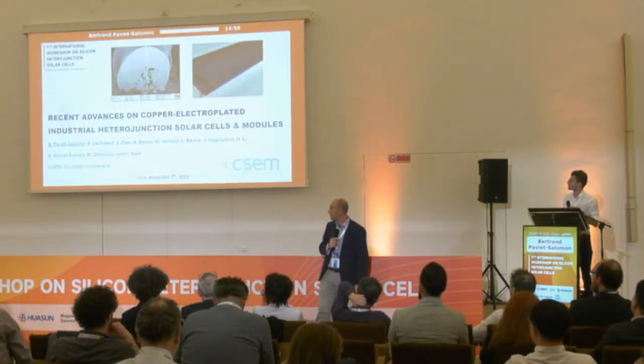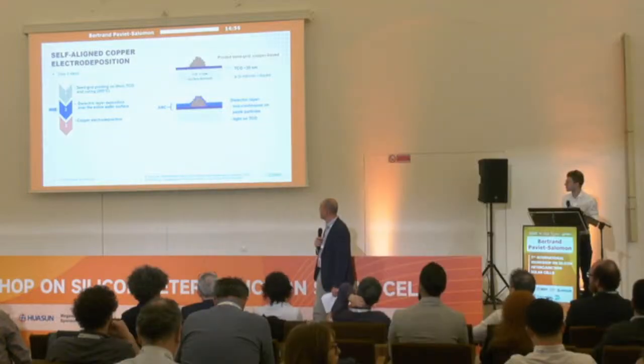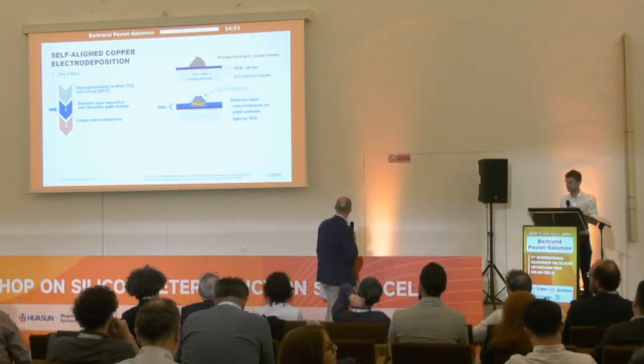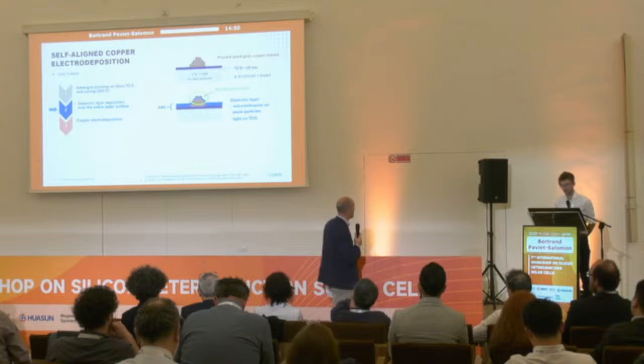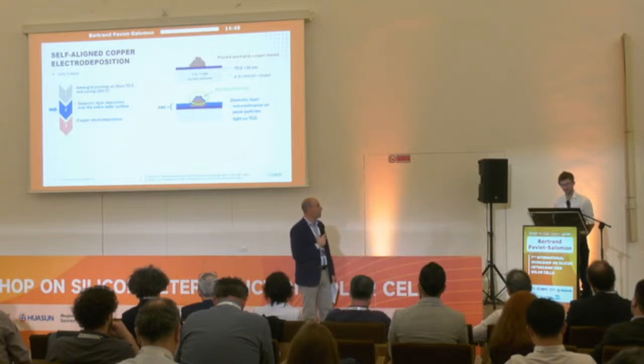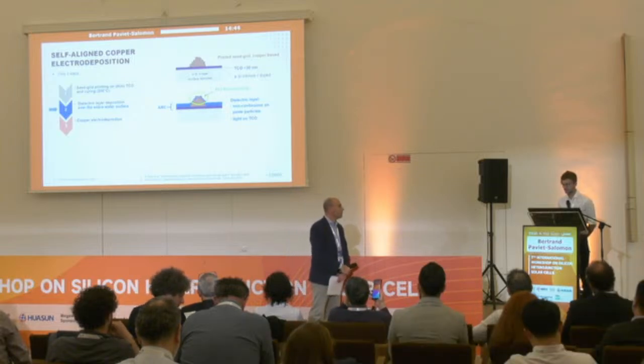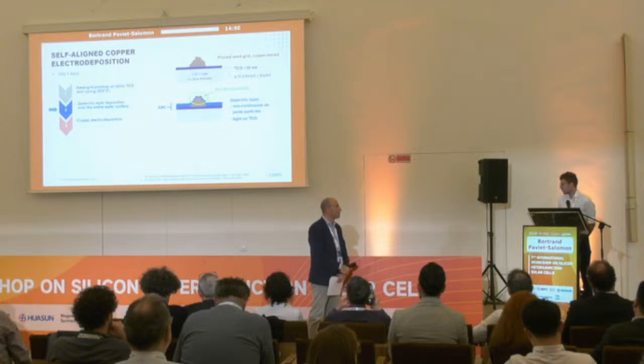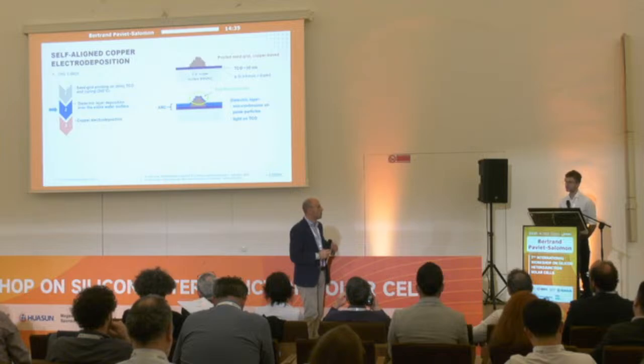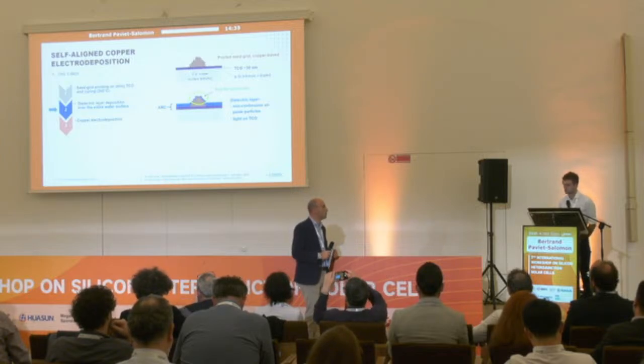Thank you very much. Thanks for the question, Olindo. The question is regarding the ARC, the deposition method for the masking layer. Basically, it's not a secret, we benchmarked different methods. Most of the results I've presented today were obtained with PECVD deposition, but we also tested ALD, and it's working really well. So you still have quite a bit of freedom to operate, to choose the best method according to your process and maybe also your design of the line.